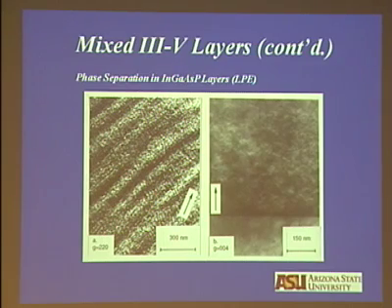What this suggests is that phase separation is two-dimensional in nature. It doesn't occur along the growth direction, but it occurs along the soft directions lying in the growth plane. If you have this arrangement, those directions happen to be 110 type. So what you conclude from these two micrographs is we have a fine scale speckle structure, whose wavelength we can determine. I'll show you in the next slide how we do it, and there is no phase separation along the growth direction.